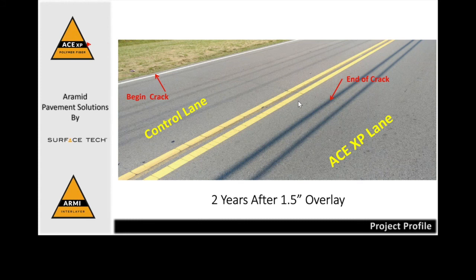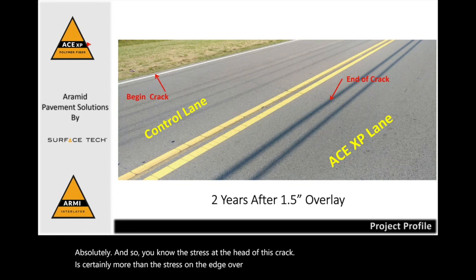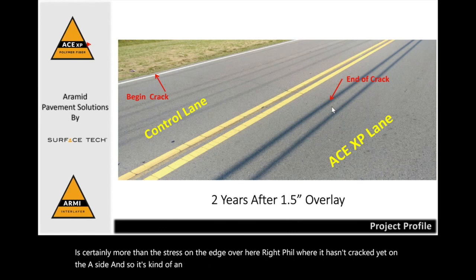So that's how those happen. And again, it just tends to move across. So I do not like side-by-side control and trials because of that. That's why most of the work that you'll see at a bigger scale is done end-to-end. However, the side-by-sides always make great pictures for the first few years. Absolutely. And so, the stress at the head of this crack is certainly more than the stress on the edge over here, right, Phil, where it hasn't cracked yet on the ACE side. And so it's kind of an unfair situation, but at the same time, we're still fighting that crack back and it's not propagating.